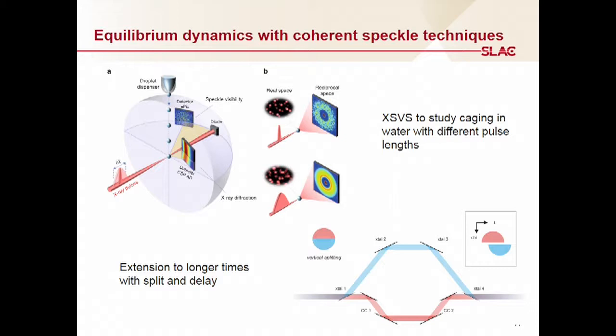So they used XSVS to study caging dynamics in water with different pulse lengths. What they did here was use the native variation in pulse duration that you can get from the LCLS machine. The LCLS machine can provide pulse durations from about 10 femtoseconds or less up to hundreds of femtoseconds. So if you want to study dynamics at that time scale, you call the machine and say, hey, can you please tune to a short pulse length? They will tune to that, and you take data using that short pulse length and then have them tune to longer and longer pulse lengths. And you see how the contrast in your speckle pattern washes out with those longer pulse lengths. That will give you some idea of whether or not you have dynamics during that time.